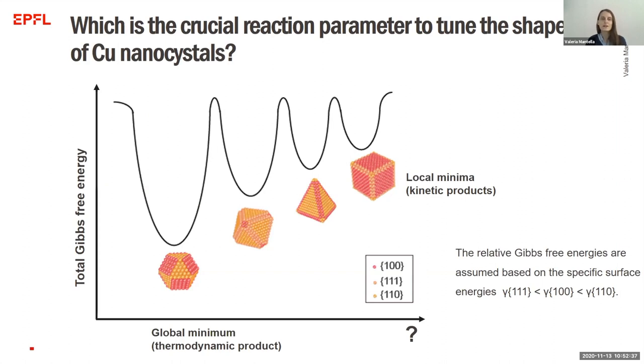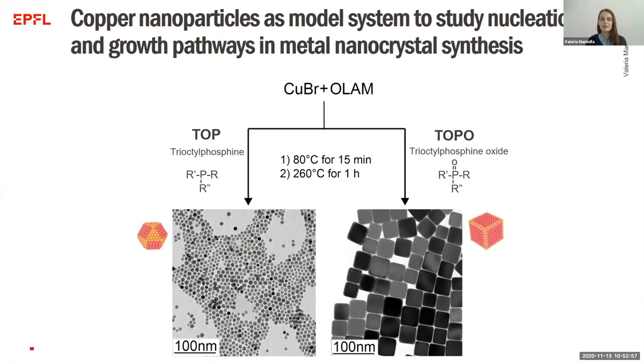We should first understand under which conditions, for example, we can obtain copper spheres that are actually truncated octahedra, or instead under which other conditions we can synthesize other shapes that will correspond to the local minima in the Gibbs free energy diagram. And so we started our investigation by following two procedures that were already reported in literature.